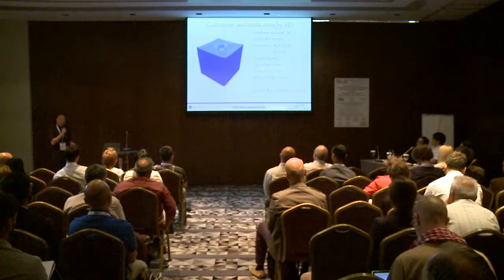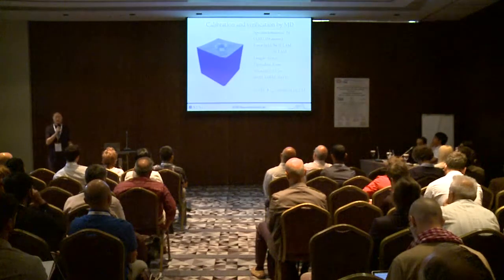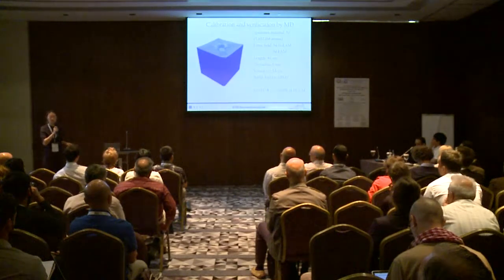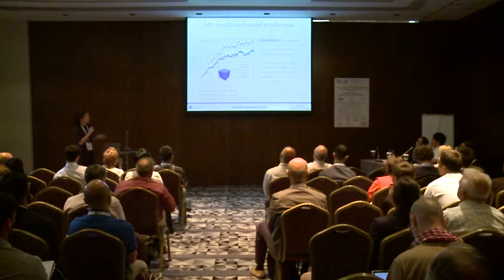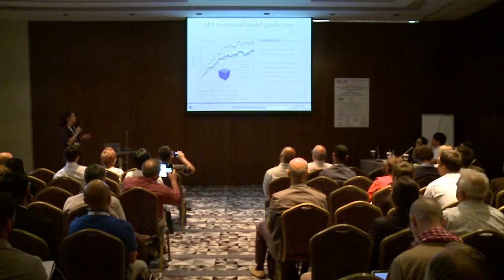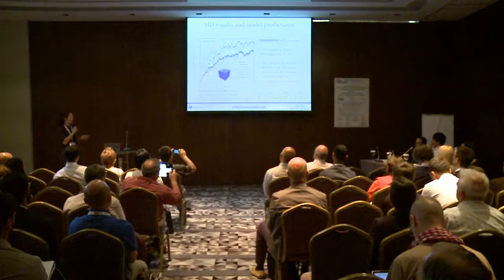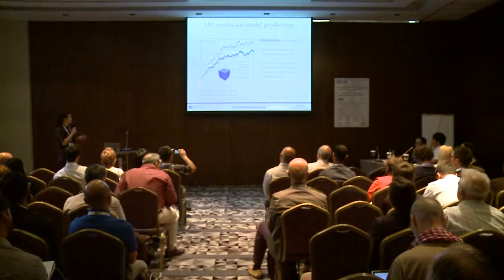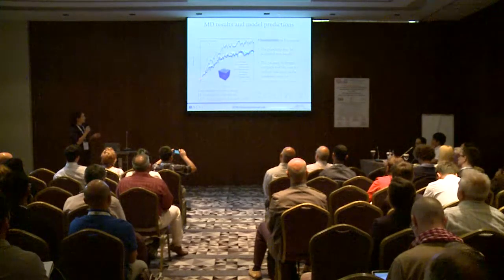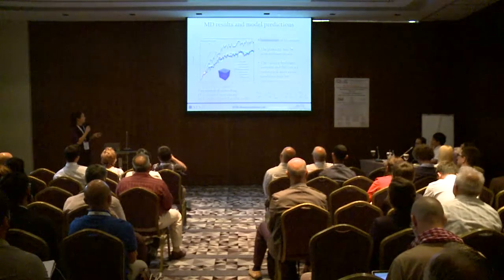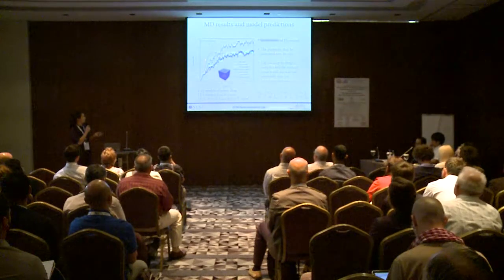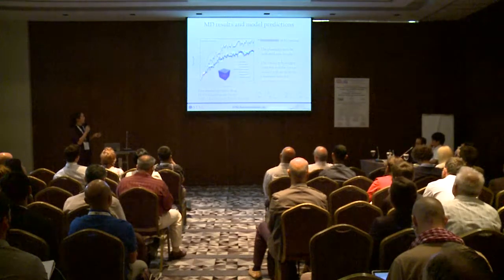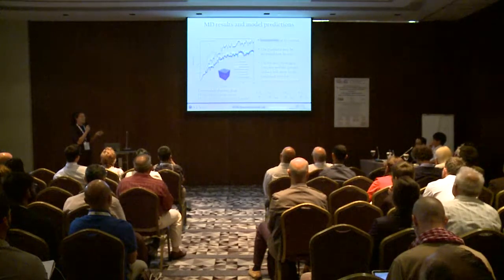Let's see some results and how the continuum model compares with the molecular simulation. This figure gives quite a lot of information, so let's spend some effort on it. First, we can see that in the elastic region, the molecular simulation results, those fluctuating curves, and the continuum model fit quite well with the Hertz elasticity model.